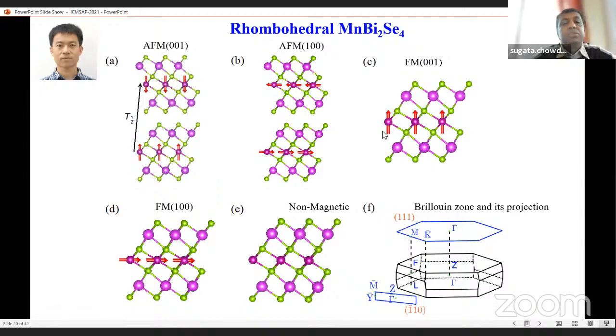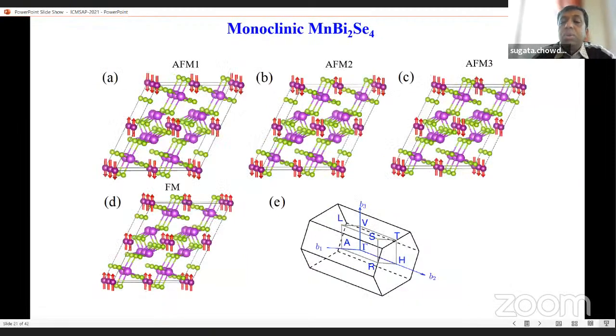Here I would like to show you the directions. This is the out-of-plane antiferromagnetic and in-plane ferromagnetic, and this is the ferromagnetic system, out of plane and in plane. He also considered the non-magnetic system for the rhombohedral structure. For the monoclinic structure, he considered different magnetic phases and how the magnetic moment direction changes: A type, C type, and all other different types of magnetic ordering for the antiferromagnetic system.